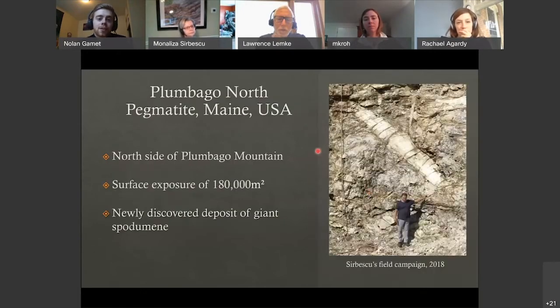The second of which is Plumbago North Pegmatite, located in Maine. This is located on the north side of Plumbago Mountain in Oxford County, Maine. It had a surface exposure of roughly 180,000 square meters, and the preliminary drilling revealed that the spodumene bearing zone was approximately 20 meters in thickness. And this is a newly discovered deposit of giant spodumene, as seen in this image on the right, with this little person next to this giant crystal.